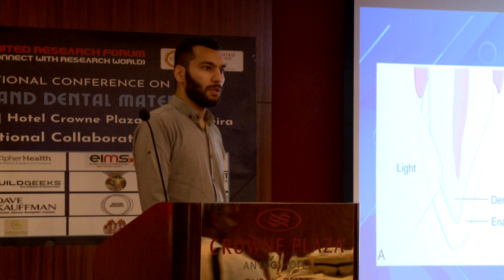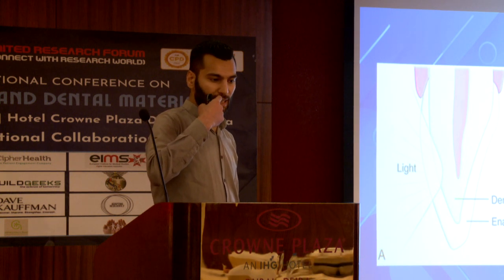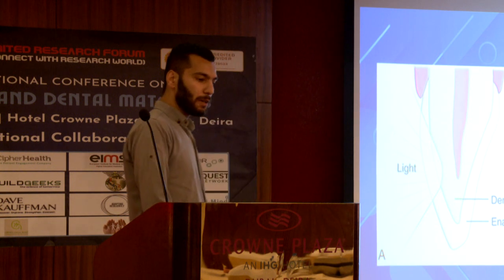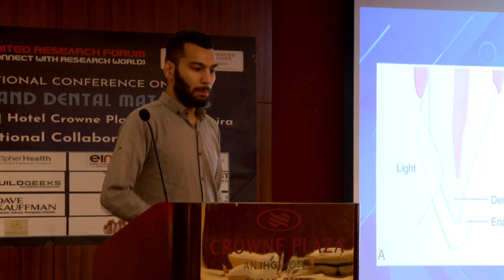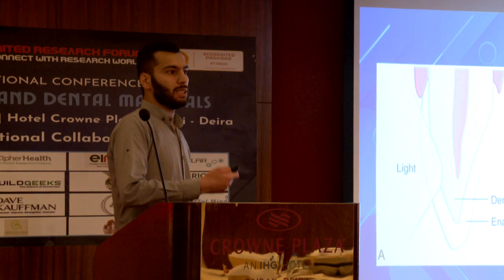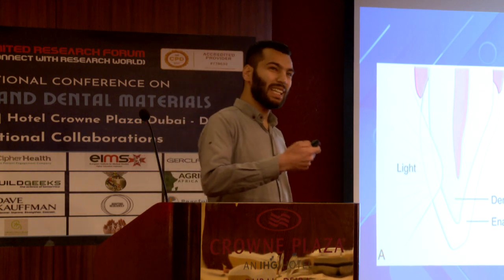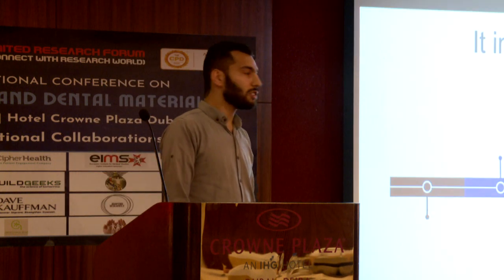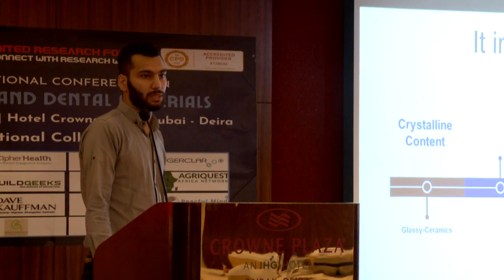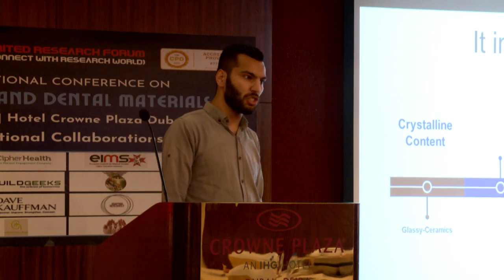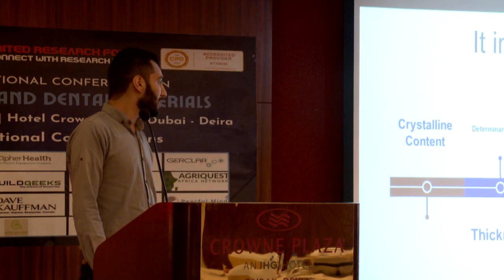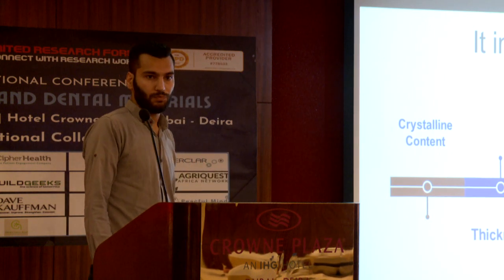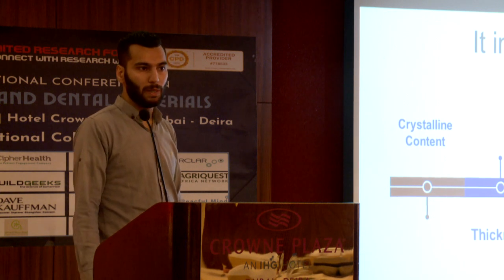This artificial material has different optical behavior. This optical behavior gets affected by many factors, mainly the underlying structure, and this interaction is due to crystalline content. In other words, it's the composition. It's affected by the thickness of this material. This thickness is a determinant factor. It's affected by the opacifier.